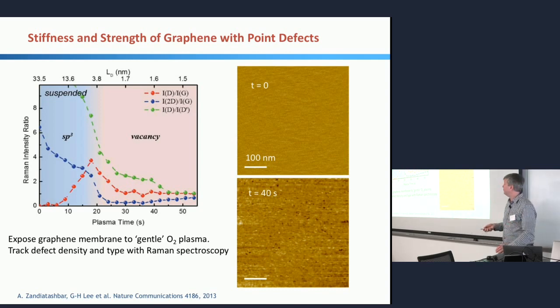And so what we did was just start putting in defects by oxygen plasma. So here we have a perfect graphene sheet by AFM. This is an extreme case. We use an extremely sharp AFM tip, and we can actually see we put holes in the sheet. But what we see in general, as a function of plasma time, is a crossover between what we call sp3 defects, where we have an oxygen bonded to the surface, and then after a while, we start to etch holes.